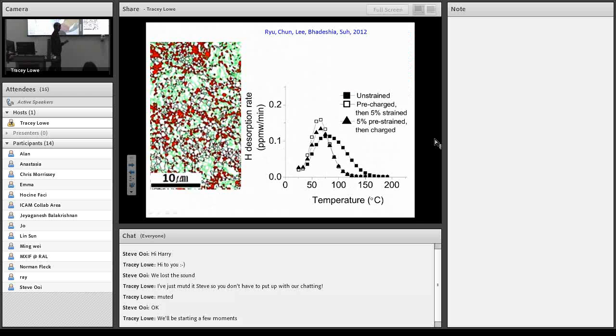The next complication when it comes to complex microstructures is that if you pull, and you've got a large concentration of hydrogen in the austenite because you've saturated the sample, the solubility of hydrogen in austenite is greater than in ferrite, and the austenite transforms into martensite, you've got a very large concentration of hydrogen in the martensite and it's going to zip through the structure. So suddenly the diffusion coefficient will be much larger because you've changed the crystal structure. And indeed, that's what you find.